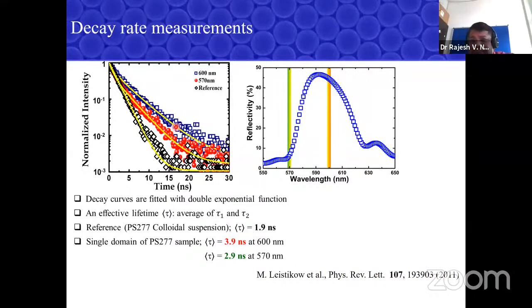And there is always a debate in the community. Is this the correct way of comparing? Is this reference correct? There is another school of thought which says this reference is wrong. Rather, one should see a wavelength dependence. If the emitter is emitting at this wavelength, the decay rate is slower, and if an emitter is emitting outside the gap, the decay rate should become fast. So we were forced to do that measurement also. We did it at 570, close to the band edge, and you can see that there is still an increase in lifetime for the emitter emitting at the band gap frequencies. So this is a clear indication that the spontaneous emission can be controlled and the lifetime changed. That means I can control the density of states of the system.